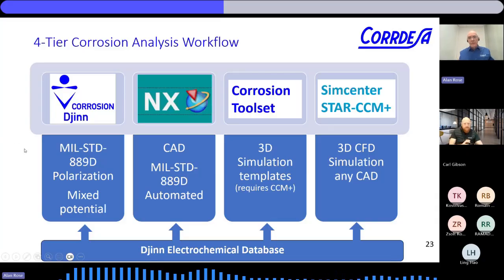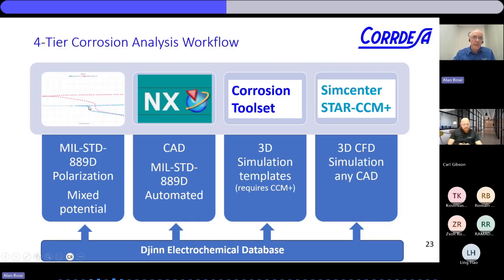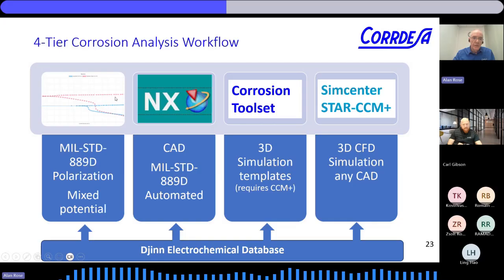So what we've done over the last few years, that was quite a few years ago, we created a SaaS software, Corrosion Djinn. It has all of that data in there, and it has data for different environments. So what this essentially does is, using mixed potential theory, if you have the polarization curves of two materials in your couple, then crossing the anodic of one branch with the cathodic of another branch will give you that corrosion rate. So that's our starting point.